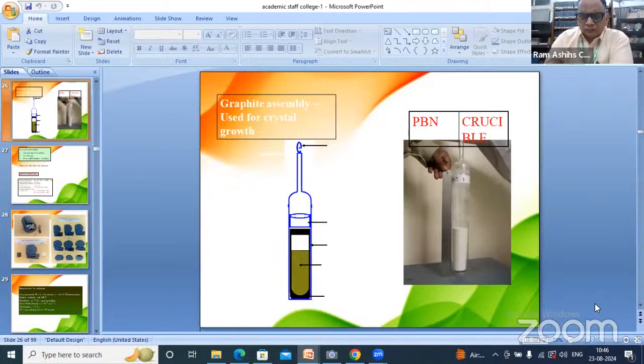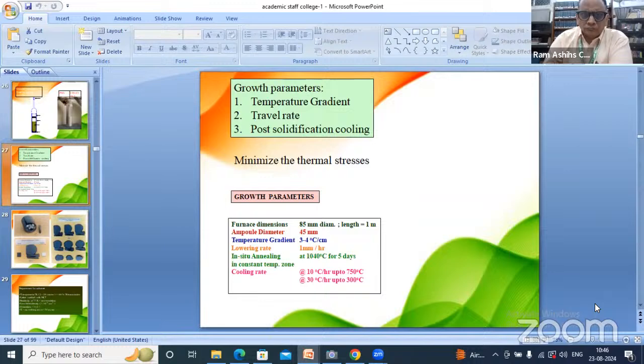This is the structure of the PBN crucible for growth purposes. Now the growth parameters are temperature gradient, travel rate, post solidification cooling, and furnace diameter, which is given here. Ampule diameter is 45. Temperature gradient is 3 to 4 degrees centigrade. And after lowering, in situ annealing is done at 1040 degrees centigrade for 5 days.